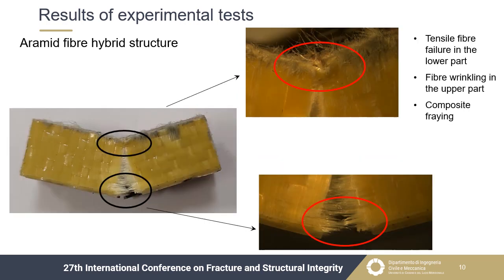As concerns the aramid specimen, also in this case the fiber tensile failure was observed, as for the carbon one, in the lower zone, together with the fiber wrinkling in the upper zone. The fracture surface of the carbon laminate was sharp and clean, while for the aramid a kind of fraying of the fibers was observed.